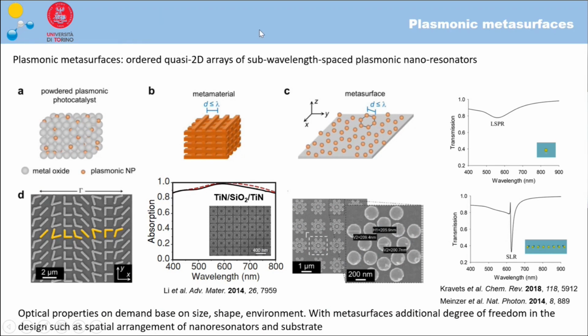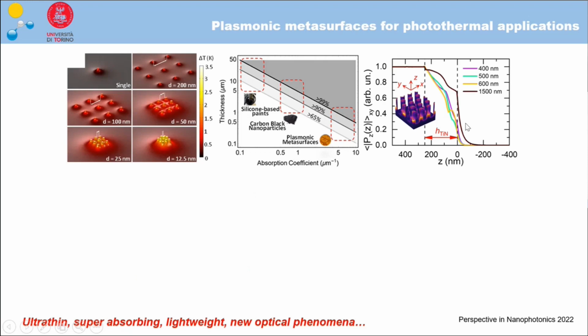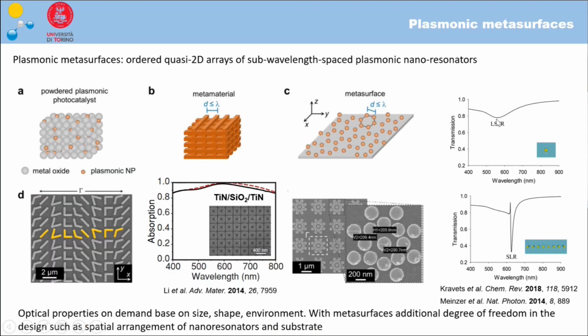As we saw before, when we have metal nanoparticles, isolated metallic nanoparticles, we have a localized surface plasmon resonance, which has an absorption band that depends on the size of the particles, on the medium, and the material which composes the particles. Then if you want to use a different region of the solar spectrum, you have to change the shape and the size of the particles, and so forth. But when you organize these particles periodically on a surface, you obtain what are called metasurfaces, which can have the optical property which you desire.